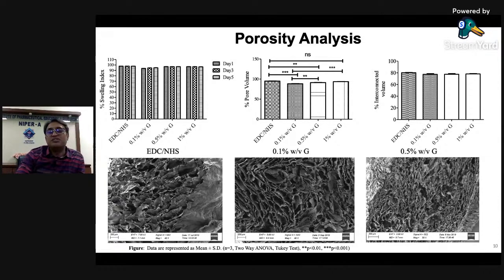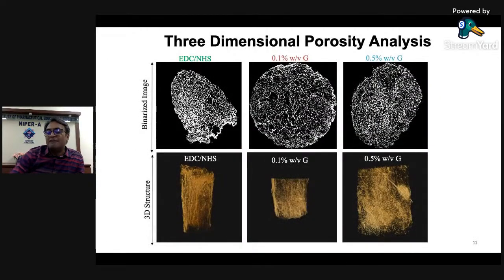Rather, we see a more distributed and thick-walled porosity present in the case of graphene incorporated material. So we further wanted to know at what level graphene has actually influenced the porosity of the material.